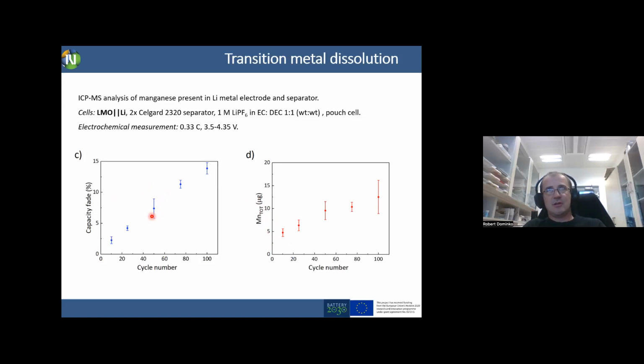manganese dissolution corresponds only to a small fraction of the capacity fade. But of course, we know that manganese dissolution creates a lot of problems on the anode, where manganese is reduced, and then the SEI becomes more electronically conductive and has to be repassivated and so on, and that creates a higher degree of capacity fading than could be expected from the manganese dissolution alone.